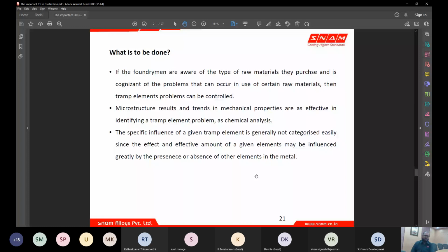We should also keep in mind that the effect of tramp elements and trace elements need not be its own individual effect. There can be a combination effect also. Say for example, arsenic and antimony put together can give you chunky graphite or spiky graphite, or it can produce degenerate graphite. And we need not think that the presence of only antimony will give you that. Even a slight arsenic, which is already available in the liquid metal, which would have been well within controllable or acceptable limits, and suddenly there is an inclusion of antimony coming into your production due to some resources. This antimony and the arsenic which is already present, in combination, can give you some defects. So the presence of every individual element and its effect should be understood and well thought out before being added to the liquid metal to produce good ductile iron.